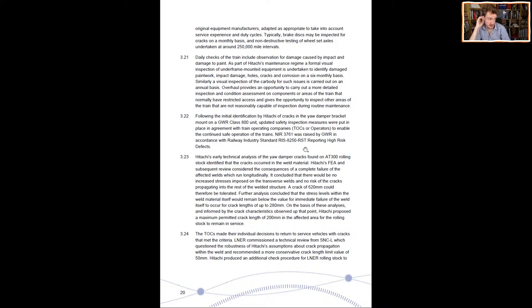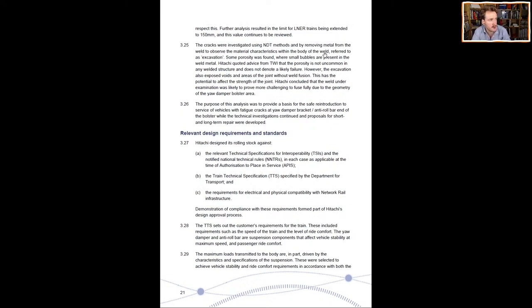Basically, you've got this analysis looking at the formation of these cracks. You can see that the crack that was tolerable was about 620 millimetres. That was tolerable, and it found that stress levels within the weld material would remain below the value for immediate failure of the weld. So you get cracks up to 280 millimetres. Basically, it proposed a maximum permitted crack length of 200 millimetres in the affected area for rolling stock to remain in service. Okay, fine. Now that's all fine and good.